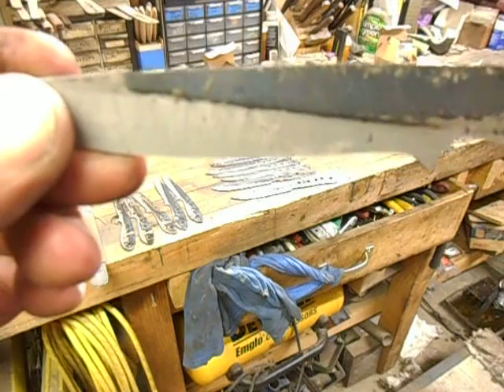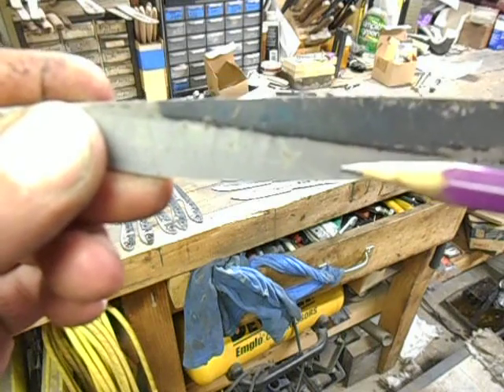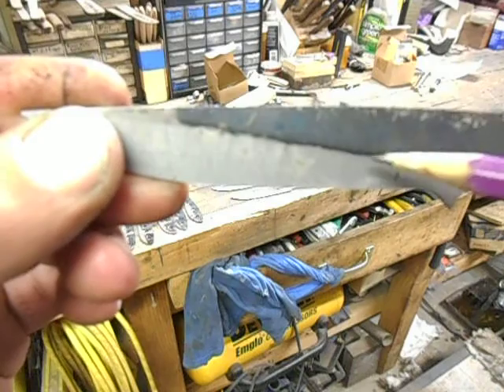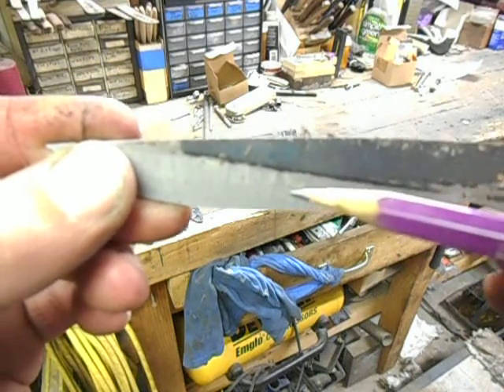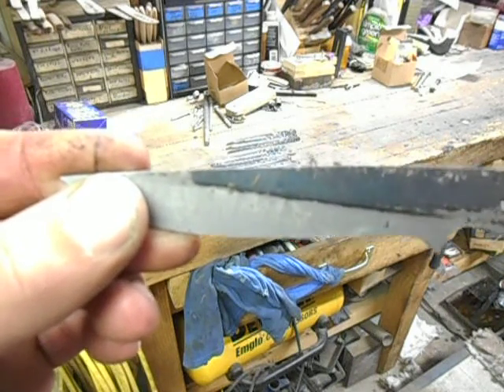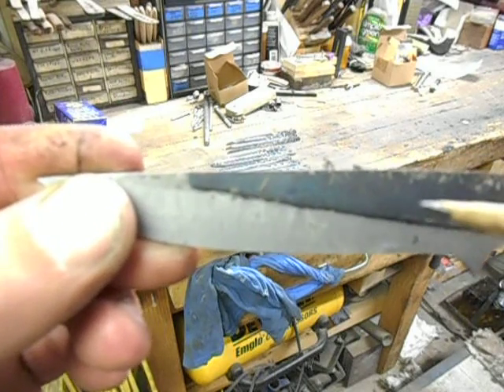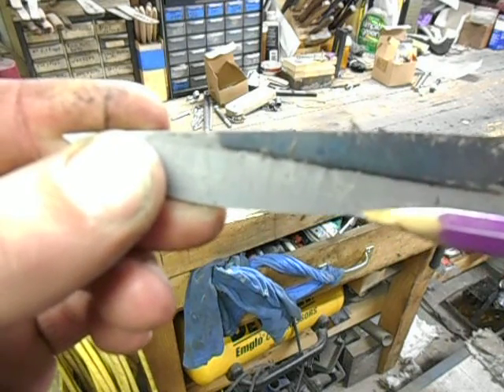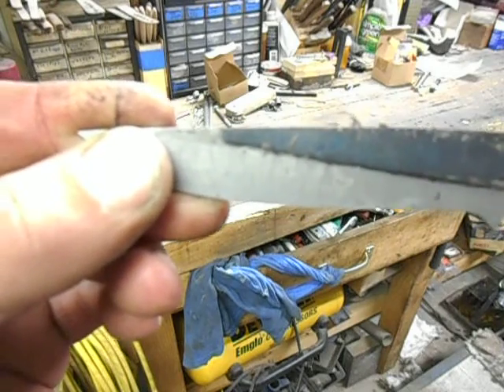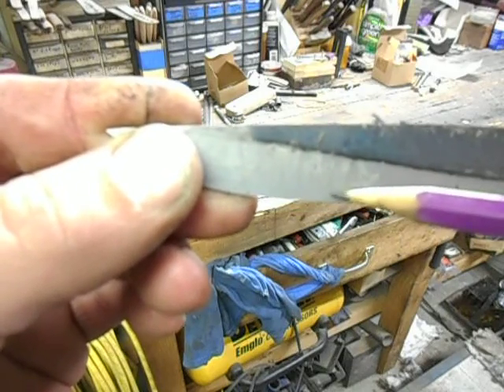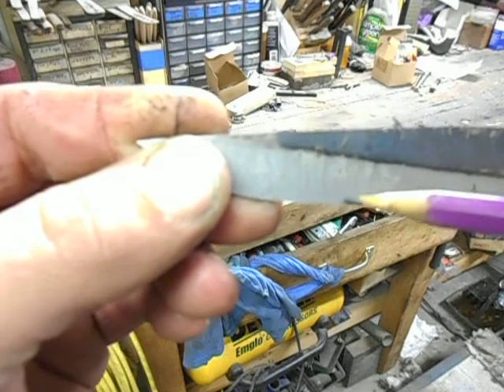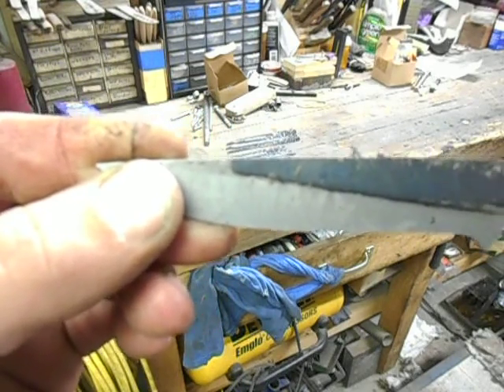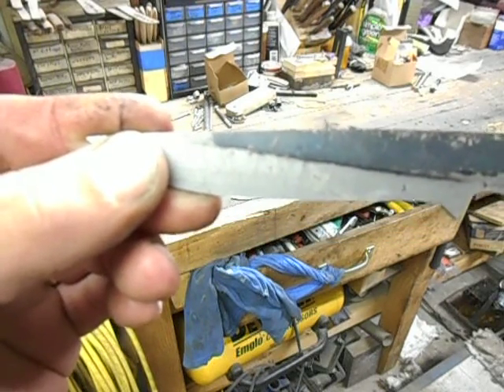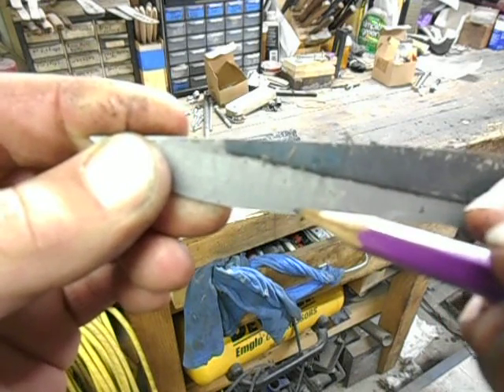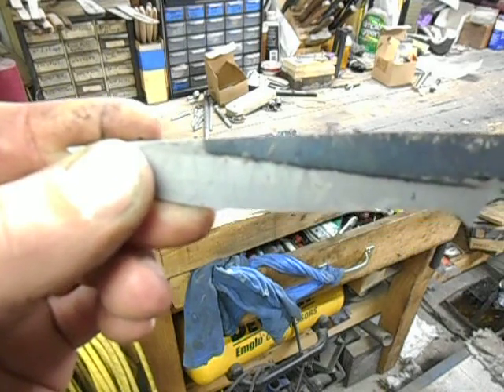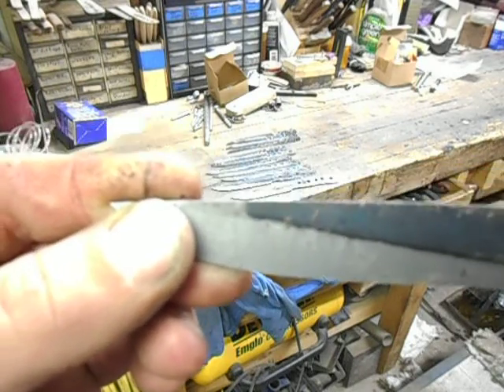But if you do end up doing a pre-heat treat grind, and I know a lot of guys like to grind as close to finished dimensions as they can on soft steel before heat treat, which, if that's what you do and you test your knives and they end up performing really good, well then, hey, that's a great way to do it. But if you do get this edge too thin prior to heat treat, and when you pull your blades out of the quench, whether it's a differential harden or a full harden, you see bits and pieces of scale hanging on at the very edge, then you finish that knife out and find that this thing doesn't cut like it should, and then you take it back to the grinder and grind off, say, 1/16 inch off of that edge to simulate using it and sharpening it, and then all of a sudden the knife starts cutting like it should.